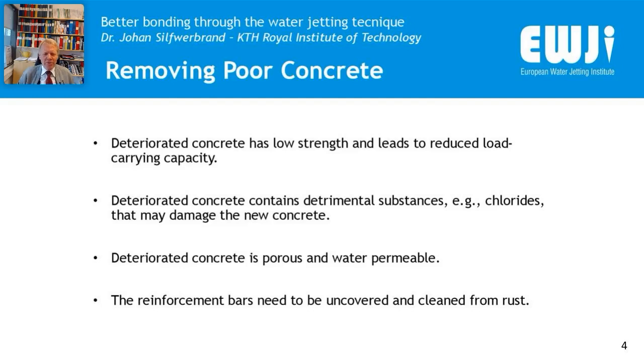And as the de-icing salt is perhaps the main damaging factor, it contains detrimental substances, that is chlorides from the de-icing salt, and they may damage also the new concrete, especially if we have reinforcement in the new concrete, and that we often have. The concrete and the reinforcement don't like chlorides, then it starts to corrode. And then also the deteriorated concrete is quite often full of cracks. It is porous and it is water permeable.